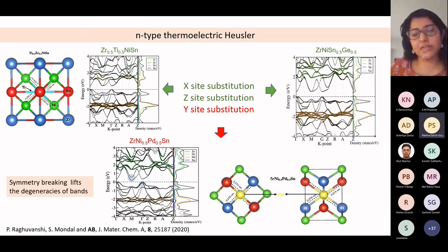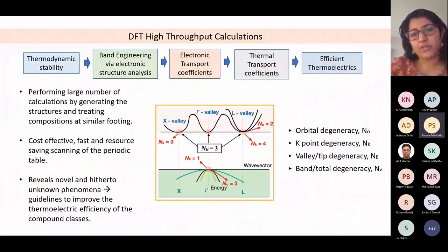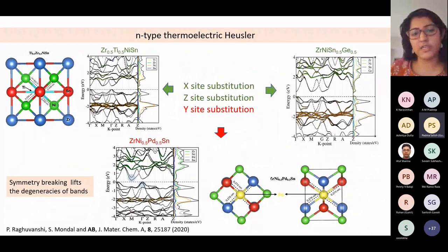So we further proceeded and performed some density functional theory calculations. In principle, we calculated all these properties, which we are not showing in detail. But here you can see, this is just to show, I'm not going to overburden you with the electronic structure here. After we have tailored all the properties, we find that if you are doing an X site substitution in this material, so these materials are XYZ materials, it's very good. On the other hand, if you're doing a Z site substitution, it's also very good, because it retains the valley degeneracies, as you see at the conduction band.